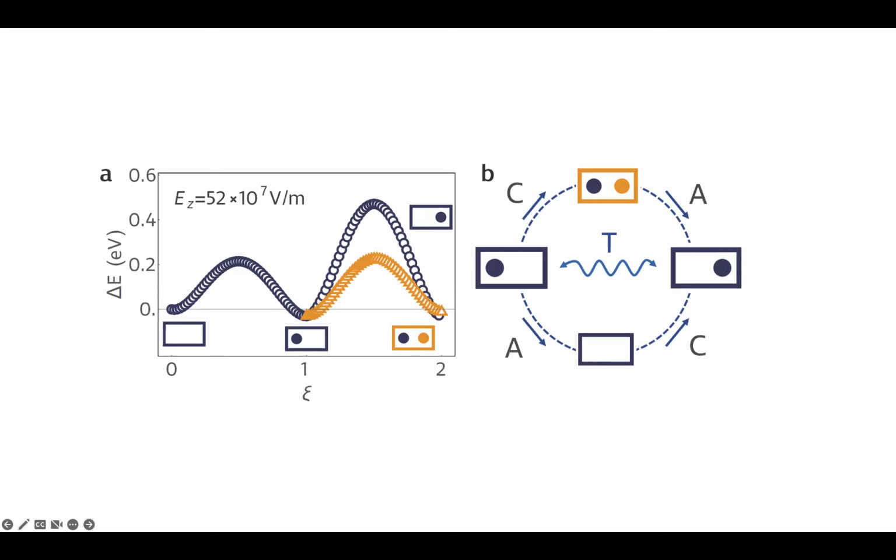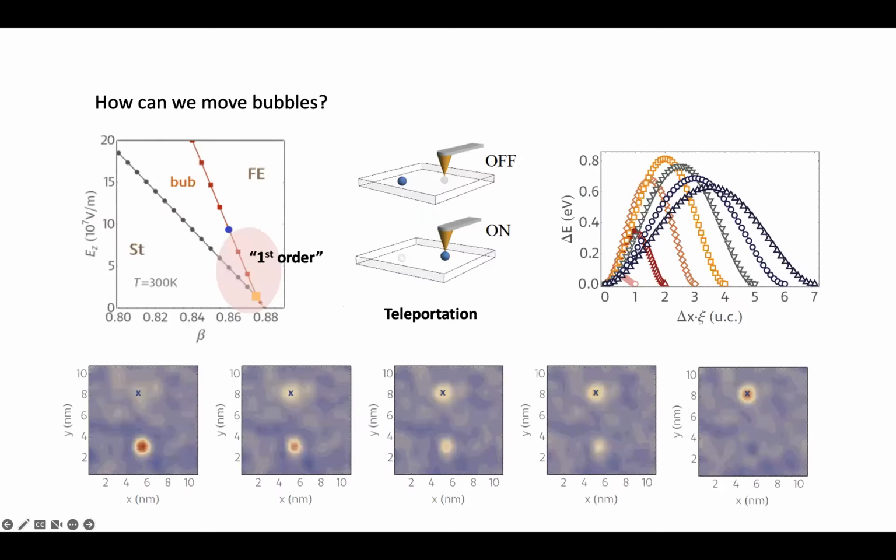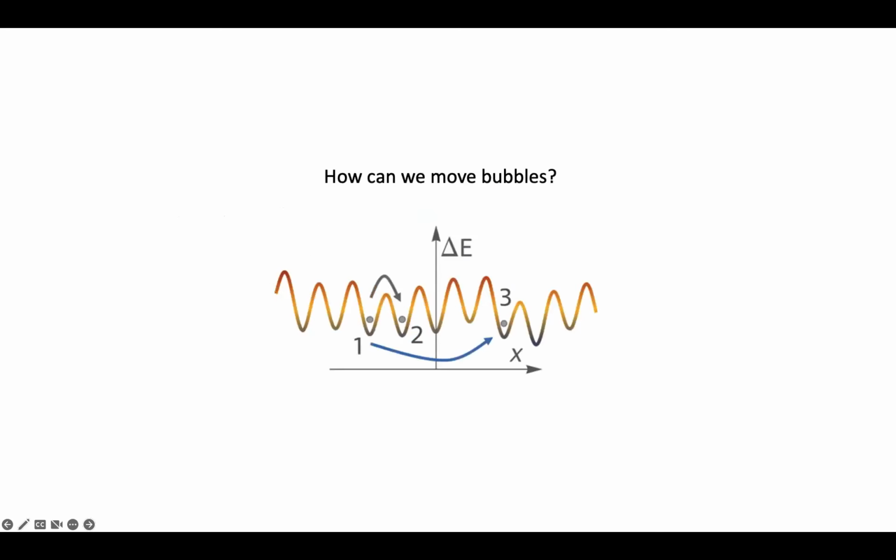Yeah, it doesn't matter, we see it both in the alloy and in the homogeneous system. The difference between those two is the energy landscape. The alloy would look like so, and in the case of a homogeneous system, it will be just flat. The barrier height will be the same everywhere, and the position of the minima would be the same everywhere.